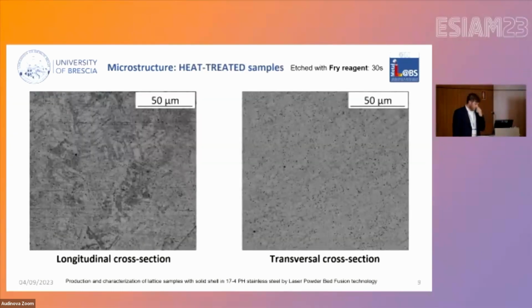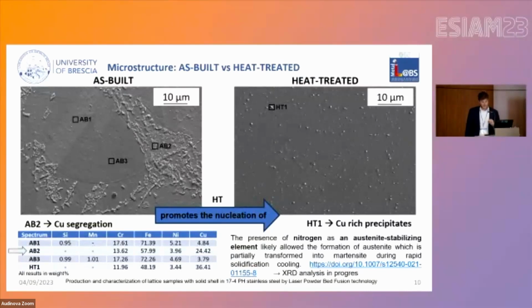After the heat treatment, we obtain another kind of microstructure. In fact, the primary microstructure with melt pools and scan tracks disappears and precipitates occur, which we can find along the grain boundaries and also inside the matrix. More deeply, we decided to study this kind of microstructure to understand which components are inside.